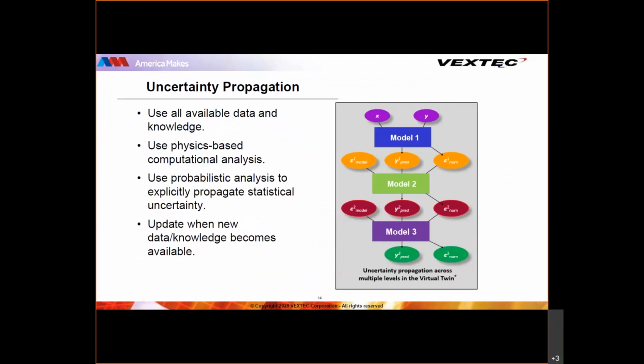Now, in recognizing the product failure as a process and not an event, and that there's much uncertainty in each stage of that process, to simulate the risk of failure, we need to propagate the uncertainty from process model to process model. By process model, I mean the actual failure process modeling, which can start with the uncertainty in the FEA model, including uncertainties in geometries and loading. And this is used along with the uncertainty in material microstructure, and also the uncertainty in the models themselves, modeling uncertainty, but propagating that uncertainty from all of its sources to the uncertainty in the final result, which is cycles